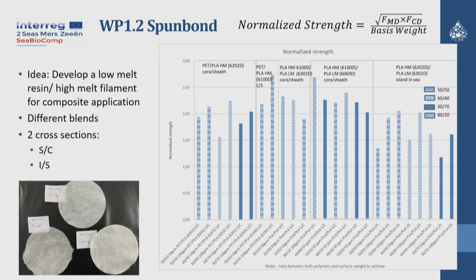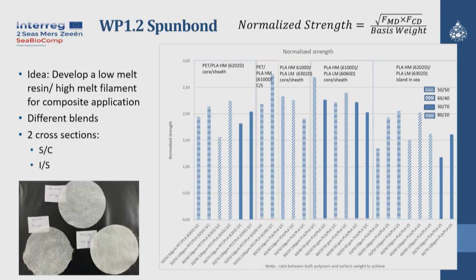But we try to produce the best non-woven for testing in composites, which was for us PLA high melt and PLA low melt, to go further. So you see that a pure biosourced polymer could lead to equivalent strength in spun bond.